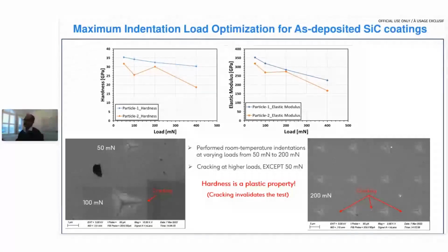load. Ceramics typically don't show the size effect as metals do, where in metals you see the increase in hardness with the decrease in load or indentation depth. So this decreasing hardness with the load was coming from something else. Similarly, for the elastic modulus, as Professor Janet was explaining, the elastic modulus is a material property, so it should not change with load or depth. But in this case, what you see is that the elastic modulus is changing with the increasing load.